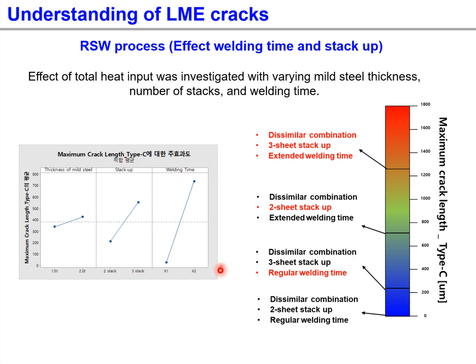The effect of total heat input was investigated with varying mild sheet steel thickness, number of stacks, and extended welding time. Thicker mild sheet and an increased number of stacks increase the level of maximum crack length. However, the extended welding time provides the largest effect on LME crack severity. Therefore, the three-sheet stack-up with extended welding time combination showed the most severe LME cracks.